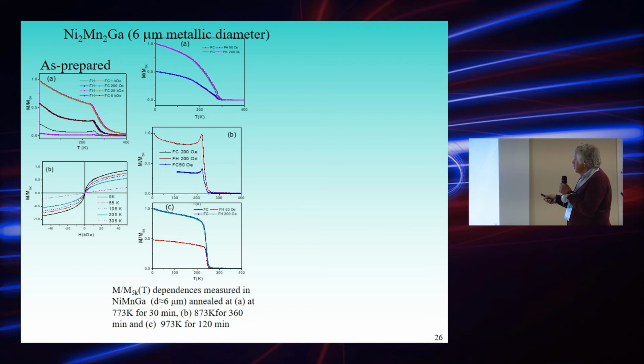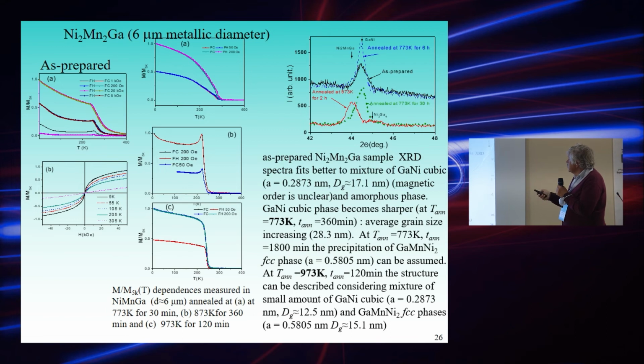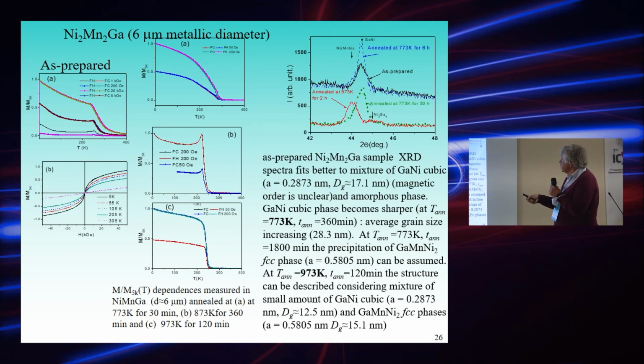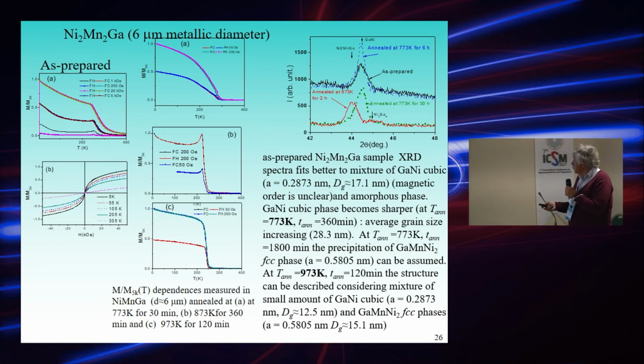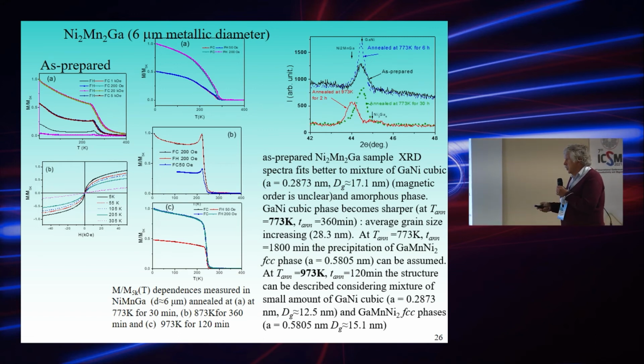The problem was that during this preparation technique, manganese was always evaporating. Therefore, we tried different compositions. For example, in the nominal composition, we added manganese. In this case, the microwires had a diameter of 6 micrometers. And again, we found this dependence on annealing conditions, of magnetization curves, and change of the structure on annealing. However, we didn't observe these features like in the case of the previous thicker microwires.